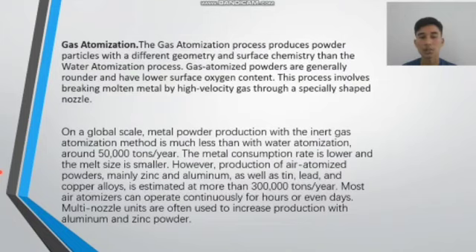The gas atomization process produces powder particles with a different geometry and surface chemistry than the water atomization process. Gas atomized powders are generally rounder and have a lower surface oxygen content. This process involves breaking up molten metal by high velocity gas through a specially shaped nozzle. On a global scale, metal powder production with the inert gas atomization method is much less than with water atomization, around 50,000 tons per year.